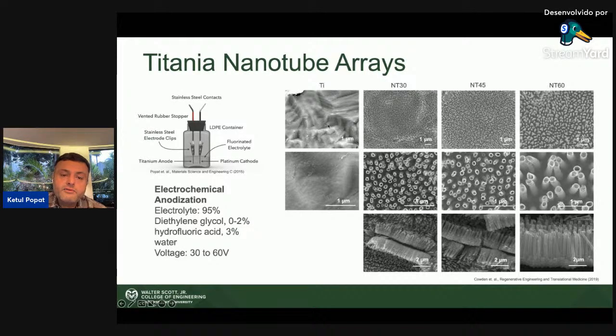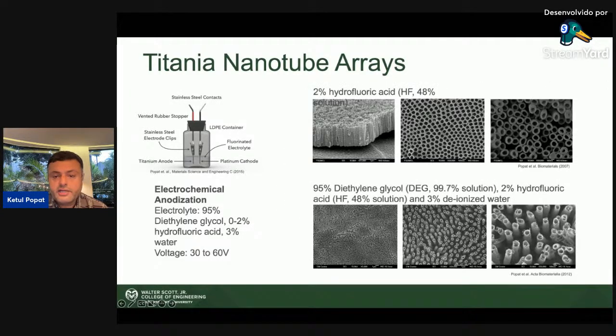And what this does is that now you have a flat surface. Obviously, you change the surface area, but you also now have a very different topography. It's a nanoscale topography because these tubes are nano in size, and depending on what voltage we use, we can get different sizes of nanotubes. Depending on what electrolyte we use, we can get different spacing. So for example, if you use a different kind of electrolyte, you can have all the tubes touch each other, or you can have all the tubes far apart. So you have some control over the topography. And what is the difference between these two is that they have very different surface energies. So when you put a cell on a surface like this versus a surface like this, the cells are going to know exactly that this is very different than this, and they will have a very different performance. So you have some control of what kind of cell response is going to happen from these surfaces.